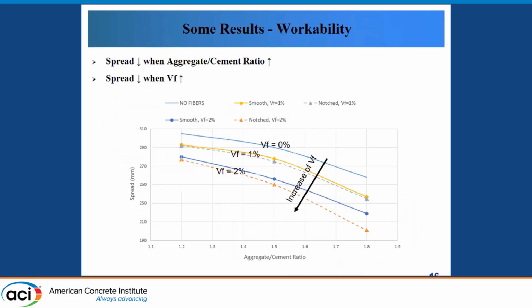As the spread decreases with the increase in the aggregate to cement ratio, the more aggregate you add, the more you lose the workability. A similar trend is seen with the addition of fibers. The more fibers you add, starting from 0, 1, and 2% fiber volume fraction, the more you lose the workability. This diagram is an excellent indicator of how change in the aggregate to cement ratio can be used to offset the effect of added fiber reinforcement.